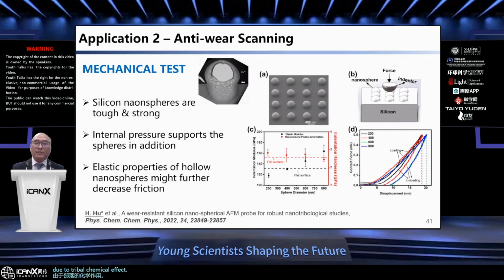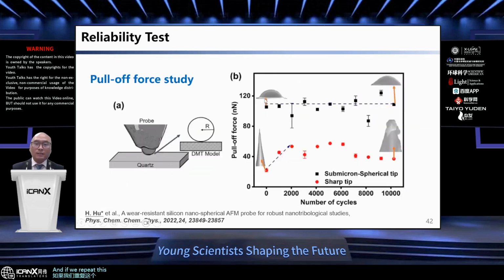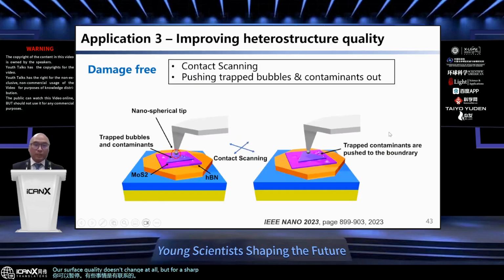If we repeat this on a quartz surface, it's even better because the quartz surface is pretty clean. Our surface morphology doesn't change at all. But for a sharp silicon tip, it even melts.